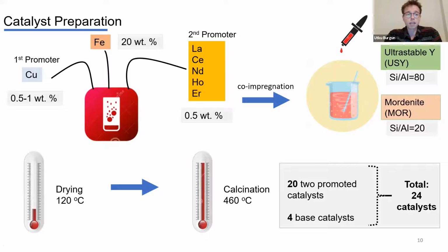In the experimental study, we selected iron as the active metal, and it was added at 20 wt% to the catalyst, and copper was selected as the first promoter, ranging from 0.5 to 1 weight percent. And to examine the effect of rare earth metals on that system, I mean iron and copper, lanthanum, cerium, neodymium, holmium, and erbium metals were added to the catalyst at 0.5 weight%.